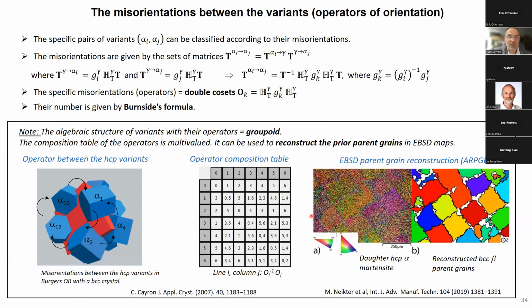I can even calculate the misorientation between the variants. And in that case, okay, it's complex. They are given by double cosets. An orientation is given by a simple coset, okay? Here you have symmetry elements. It's a matrix. Here it's a subgroup of matrices, but you can take one of them in this subgroup. It doesn't matter. And you have the orientation relationship between the parent phase and one of the variants. You can do that for another variant. And if you want to go from one variant I to a variant J, you take the inverse of the first matrix multiplied by the second matrix on the right, and you get that. And you see here, you have what is called the double coset.